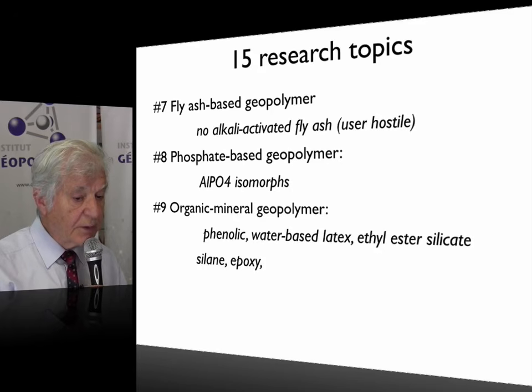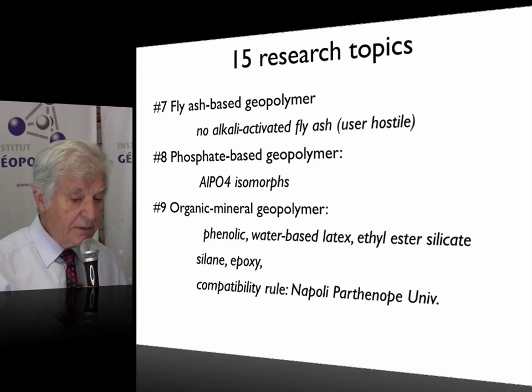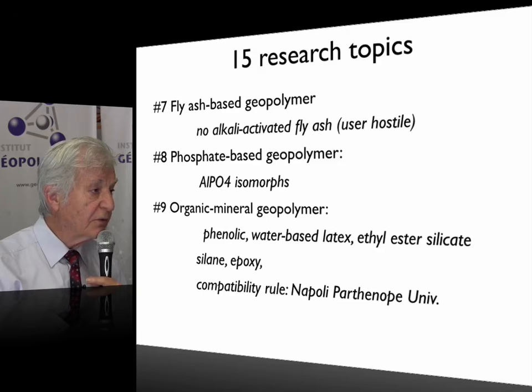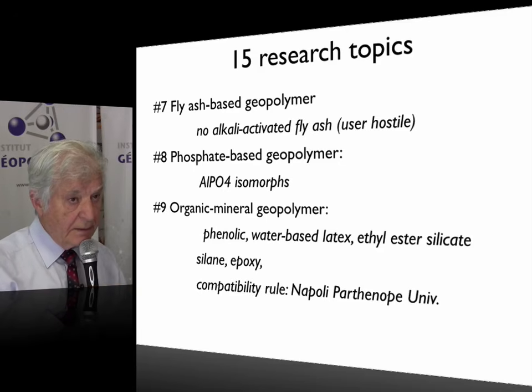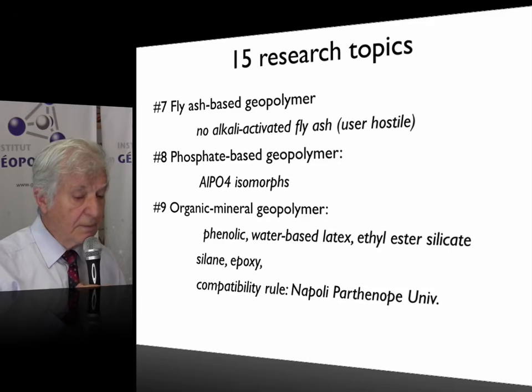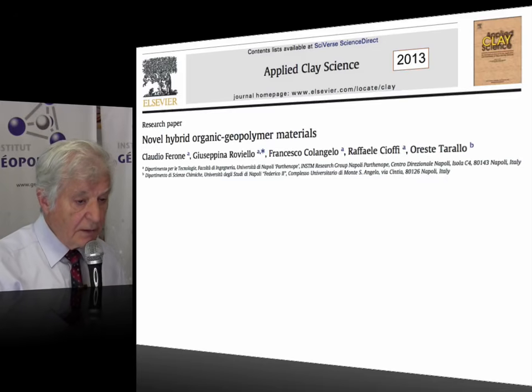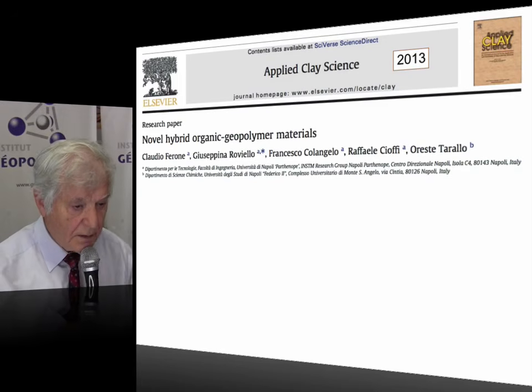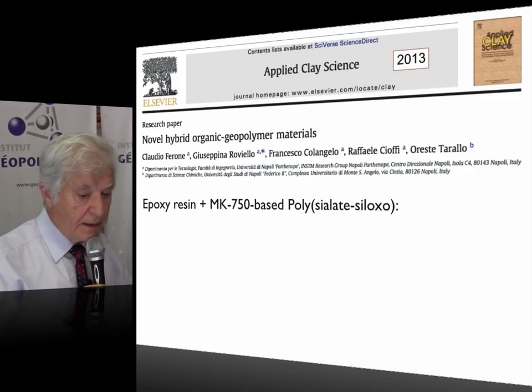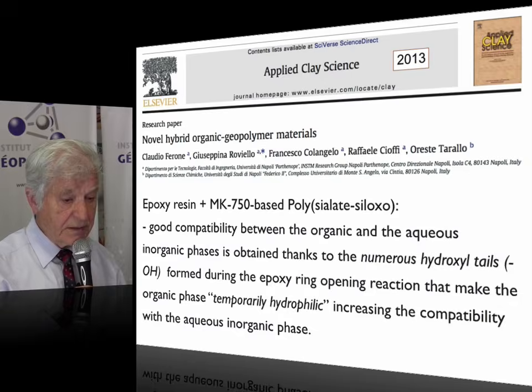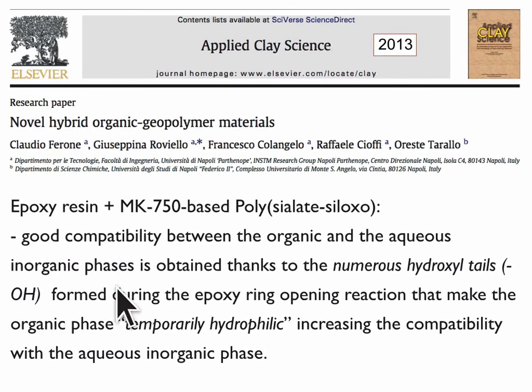And then we have the organic mineral polymers, those that include the phenolic, latex, silicate, silane, epoxy, and the colleagues at Napoli Parthenope University have discovered a compatibility rule between a geopolymer medium and an organic one. Normally they are incompatible, and this has been published in 2013. Novel hybrid organic geopolymer material, epoxy resin and metakaolin based poly(sialate-siloxo) mixed. We obtain a good compatibility between the organic and the aqueous inorganic phase thanks to numerous hydroxyl groups, such as OH, that are formed during the epoxy ring opening reaction that make the organic phase temporarily hydrophilic, increasing the compatibility with the aqueous inorganic phase.